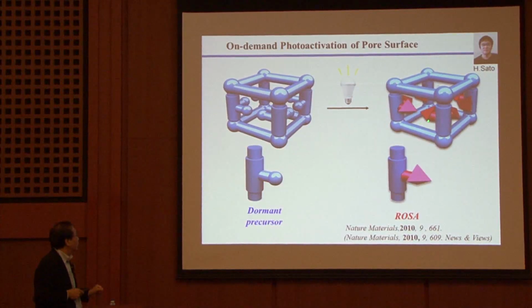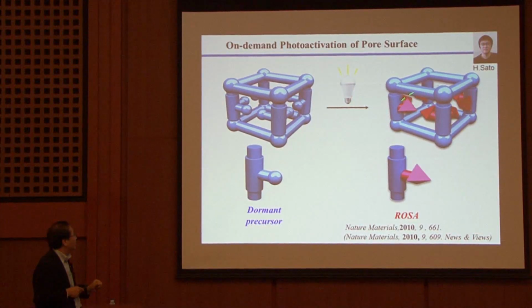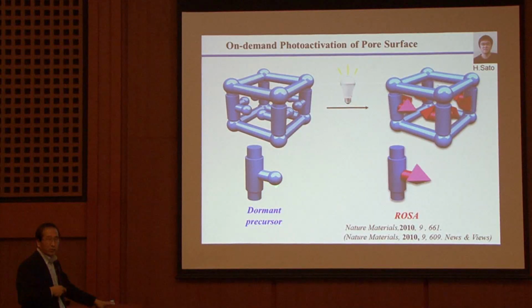We try to have a very reactive surface in the channel, but of course it is very difficult if we use this kind of reactive species at the beginning of the synthesis. So our idea is to use a dormant precursor. We use the precursor, synthesize the framework, and then irradiate it and obtain this kind of framework. This is our idea.